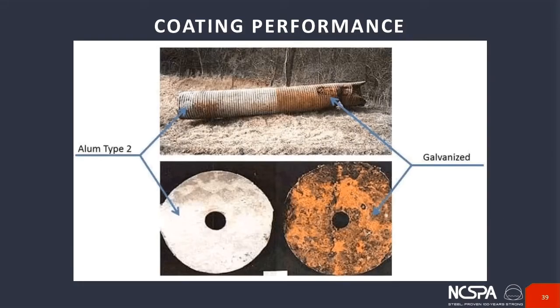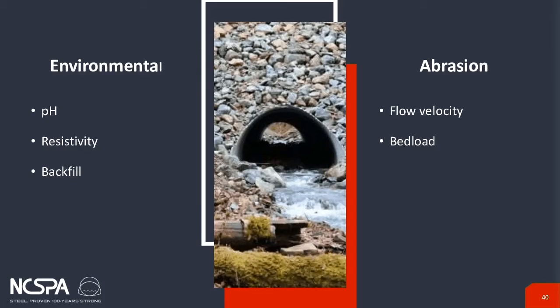But you know, at the end of the day, we know exactly why this happened. And the pH in this particular instance is why that particular pipe looked the way it did. So the pH in that particular instance was a little bit under 6, and the resistivity was around 2100. So pH and resistivity are two of the primary drivers of the service life and durability of these particular coatings. That's derived from the soil around it, the water that runs through it, the backfill above it, right? And what also percolates through that backfill. And then the abrasion levels are what obviously flows through the pipe. Flow velocity and bed load. Now, without bed load, the velocity doesn't really matter. It's the particles in the water that create the abrasion, right?